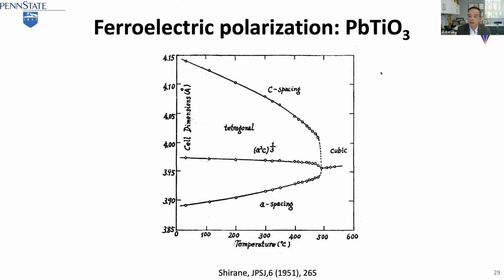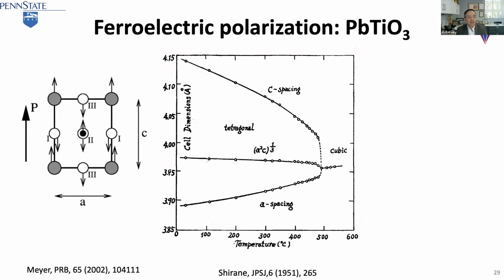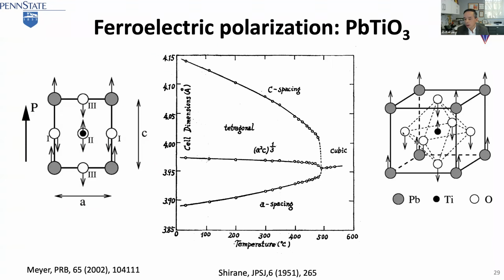It's ferroelectric polarization, lead titanate. You know that at low temperature, this is the lattice parameter as a function of temperature. It's the c/a ratio, and you get tetragonal. And when the temperature is high enough, it becomes cubic. You measure the lattice parameter by X-ray. If you think about the bird in the cage, you have the bird and the cage separated, then the bird in the cage, right? It could be very similar to that. So you have the polarization, the tetragonal displacement, then you increase temperature and it becomes cubic when you do the experiments. But remember, atoms are not static, they move all the time.